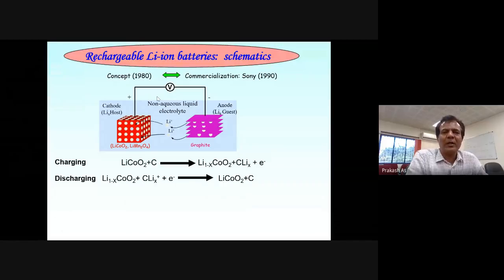So this is the schematic of the rechargeable lithium battery, how it works. As I said, you have cathode materials. Typically, the cathode materials are lithium-containing transition metal oxides like lithium cobalt oxide, lithium manganese oxide, or lithium iron phosphate, wherein the structure should be a layered compound or a 3-dimensional structure for lithium ion diffusion. The negative electrode is graphite, and these are separated by a separator soaked in the electrolyte. The electrolyte is typically a non-aqueous organic electrolyte which conducts lithium ions. Typically we use lithium hexafluorophosphate in ethylene carbonate or dimethyl carbonate as solvents.